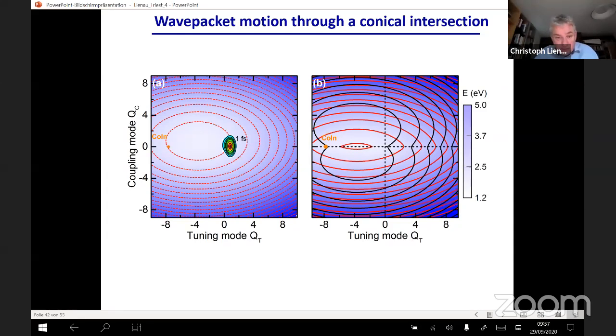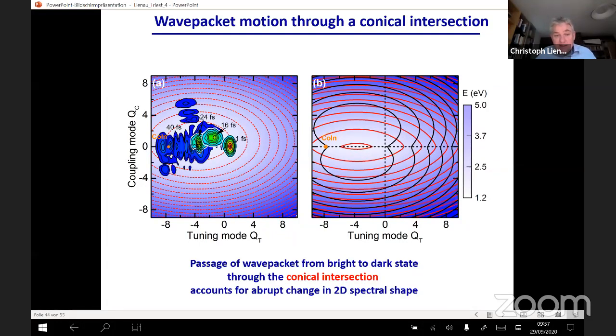To introduce this to you without going too much over time, I want to show you just the simulation. That's the simulation of an electronic wave packet that we have placed on such a potential energy surface showing a conical intersection. We launched the wave packet optically somewhere in the optically bright excited state. Then we calculate its time evolution. It stays a nice Gaussian wave packet. But as soon as it reaches the conical intersection, it sees a different electronic surface, and it basically spreads out in configuration or phase space. So it changes completely its position here. And this spreading, that's what we have seen in the experiment.